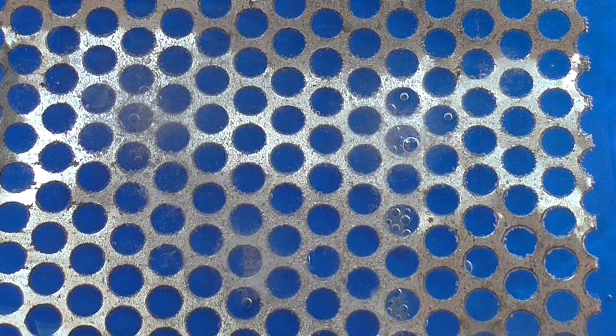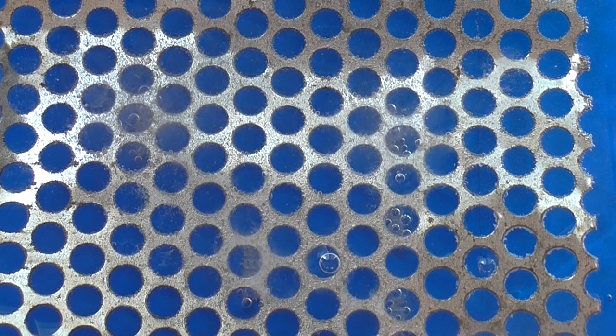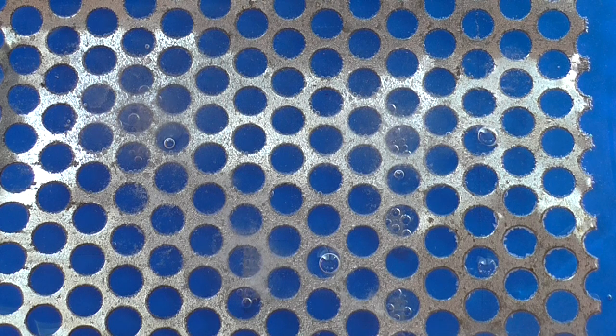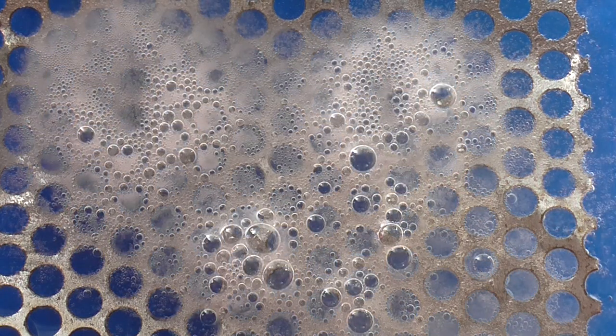It goes without saying, but this should be done in a well ventilated area as vapors and explosive gases can be released. I let this run for about 10 minutes at 300mA, which is a bit longer than I would normally leave it, but I wanted to etch it nice and deep so it shows up clearly on the video. You might want to experiment on a test piece to see how long is needed.